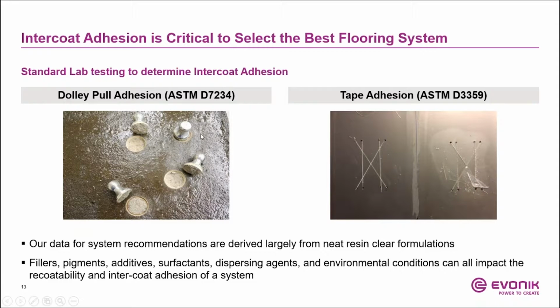So here are a couple ways to do a quick check to see if these layers stick to each other. One is the dolly pull adhesion testing, ASTM D7234. Once you put on all those layers, you want to do a dolly pull and make sure that the failure occurs at the concrete. Another one, a quick and dirty test, is tape adhesion. Again, you apply multiple coatings onto the substrate, and then you do the scribing with a knife, and then you pull a tape and pretty much see where the failure is occurring. So again, you do not want the intercoat failure to occur, okay?